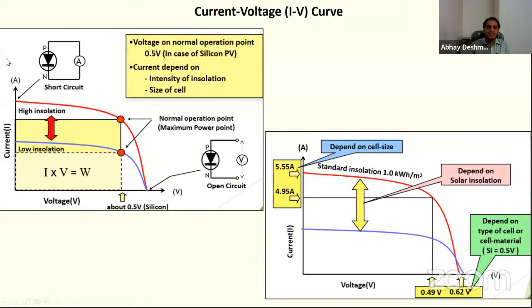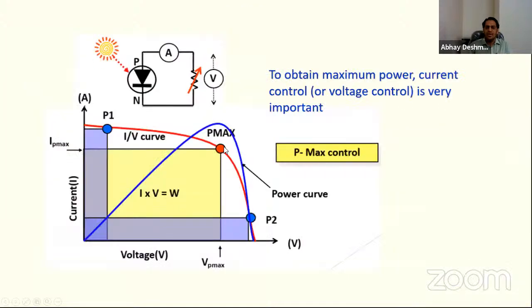And this current then gets modulated with your cell size as well as the atmospheric conditions, or the incident energy, which we call the insolation of your solar cell. So if you have high insolation, you will have a higher current. If you have low insolation, you will have a low current, right? And then we need to find your Pmax, which gives you Imax times Vmax. Okay, so the maximum power available for your device which you have made. If you take this Imax and Vmax and vary them over here, you can calculate the maximum power available with that particular device which you have fabricated.